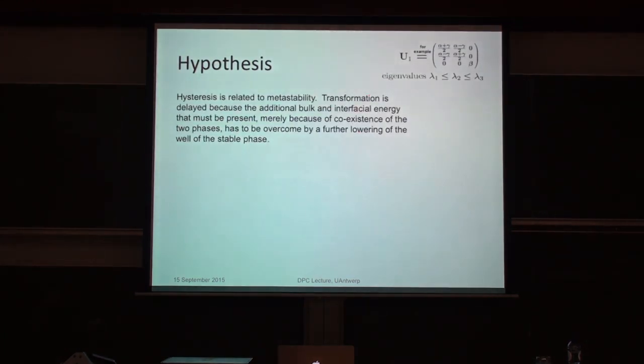So transformation is delayed because the additional bulk and interfacial energy that must be present merely because the two phases are next to each other has to be overcome by a further lowering of the free energy of the stable phase. So that's something you could study, and we began to study this, but we realized, also with a number of collaborators, that there's an experimental way to look at this effect of compatibility on hysteresis. And you can do it the following way.